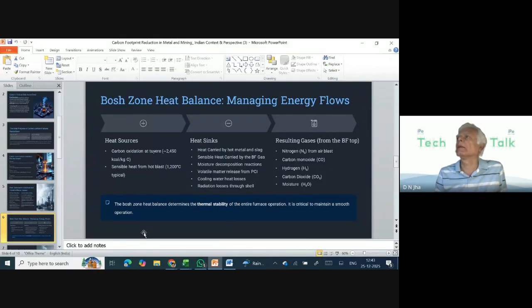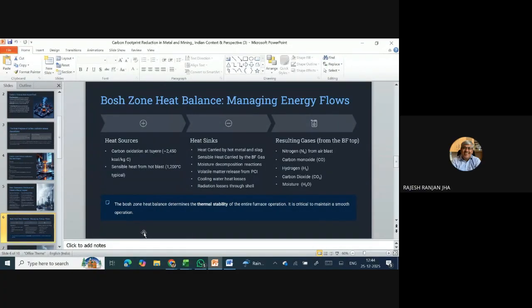Okay, so this is one. Second, if the heat requirement is higher, then we will have to use some extra amount of PCI, because that is providing carbon and also substituting the steam. The third thing that we will do, without disturbing anything else, is increase the hot blast temperature, because that's a sensible heat which is going there. It's a direct heat. So these are three examples of addressing the heat requirement, if that is coming as the bottleneck. Whereas if reduction is coming as the bottleneck or the critical factor, in that case, what will we do? We'll have to improve the reducibility property of the burden. Is that clear? Yes, yes, absolutely.